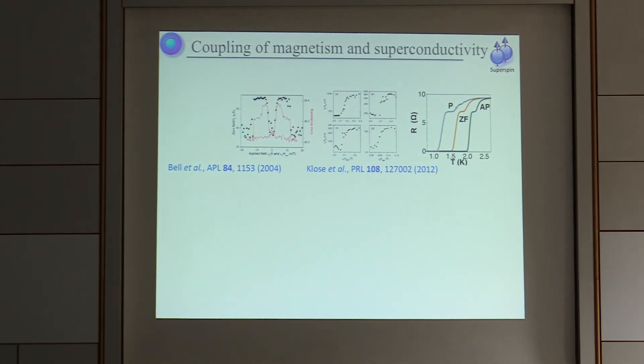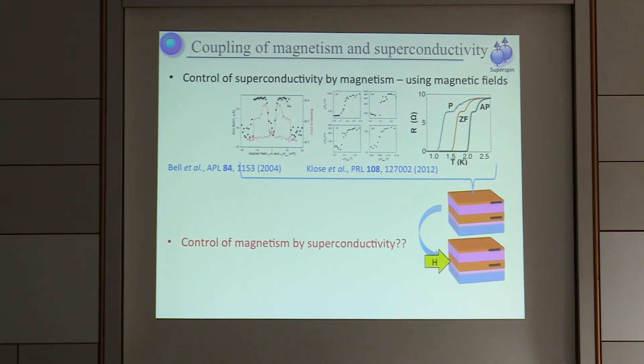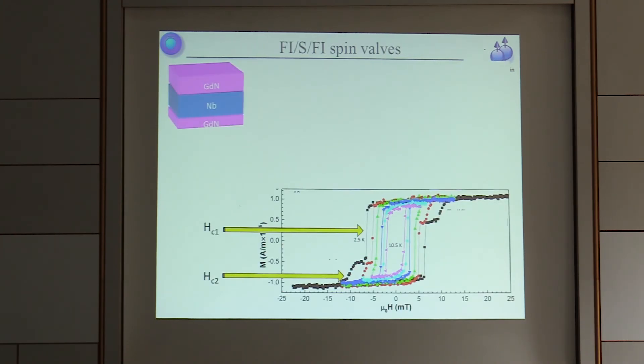There are lots of ways in which you can manipulate magnetism to control superconductivity, as shown in several previous talks. What you really want is some method by which the superconductivity can control the magnetism, because then you've got a closed system and can start to design circuits which might exploit these interactions. We focused on this behavior, and in particular the emergence of this second coercive field and its fairly rapid increase when you hit the superconducting state.